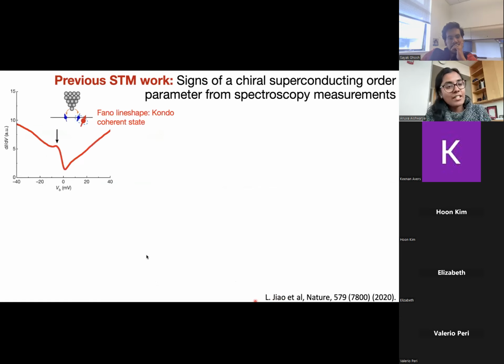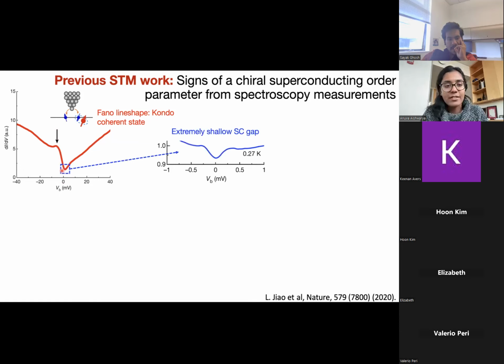Low energy spectroscopy shows this very familiar Fano line shape, which generally happens when we have a resonance in the system. And this resonance is the Kondo coherent state in UTe2. If you fit it, you will get a Kondo temperature that agrees with transport measurements. Now, if you zoom in close to the Fermi energy, we find an extremely shallow superconducting gap. It barely suppresses by 10% at 270 millikelvin.